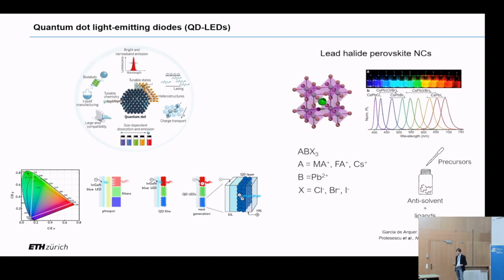And among all the possible materials that you can make a quantum dot from, we mainly study lead halide perovskite nanocrystals, which after three days of conference, I don't think we need to introduce further. Maybe one thing which is interesting for nanocrystals is that we already heard of their unusually high tolerance for defects. Well, that's very handy to make nanocrystals, because we can synthesize high quality, so high PLQY, lead halide perovskite nanocrystals under quite mild conditions, like room temperature, even in one-pot synthesis.